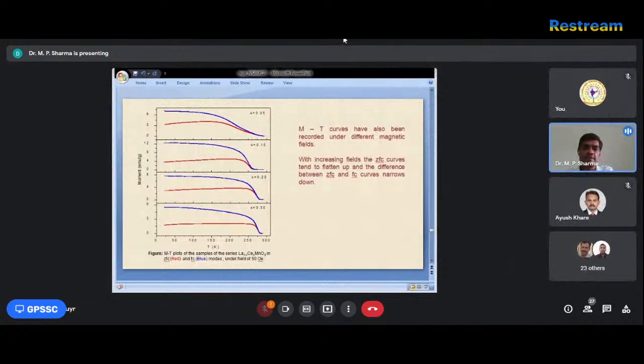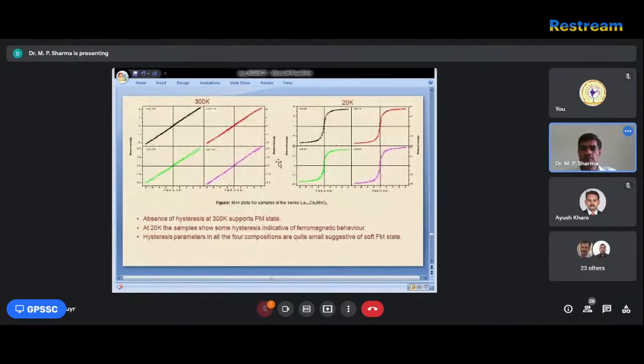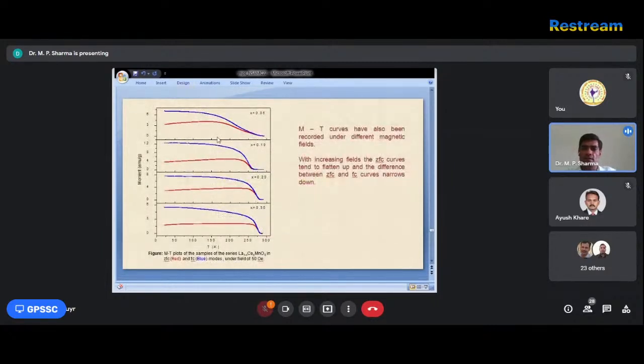So in the calcium substituted case, we can say that all these samples again show the PM to FM states. These are systematically ordered systems, going from PM, and this M-T curve also shows measurements recorded in different fields, which is again the ZFC and FC we already defined. So if you look at x equal to 0.05, the system is